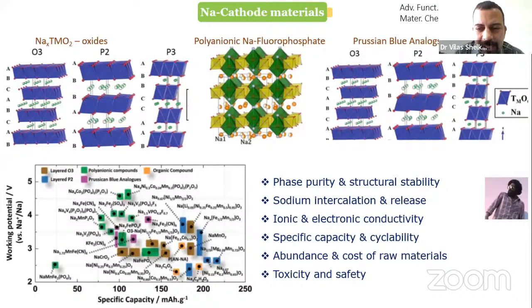The ionic and electronic conductivity of a material plays an important part, because the number of ions transporting from one end to the other end is defined by the ionic conductivity of the material. And at the same time, electronic conductivity is important, because if the material is insulating, the electron transport happening in the outside circuit will not take place. So both ionic and electronic conductivity play an important role for this material.